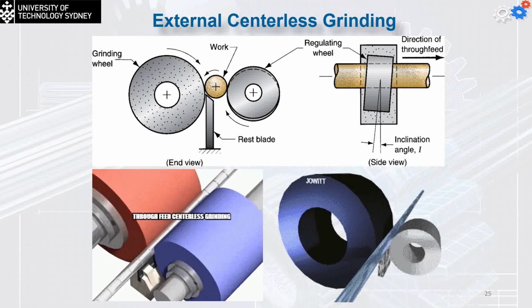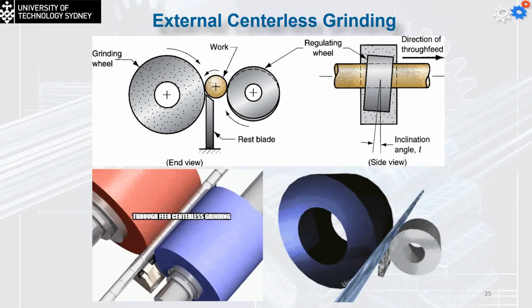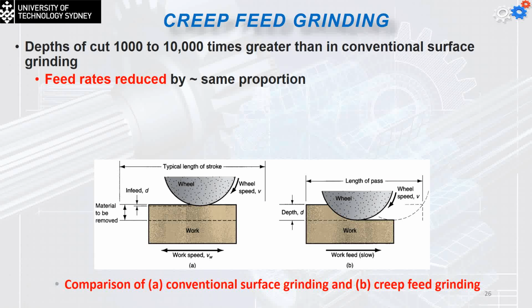We have two different types of grinding, one of which is the creep feed grinding process. Now, that's the normal case, the conventional surface grinding. We just remove the material in a very thin layer to expose a new good surface finish. But sometimes we can use the same process to remove the material at a higher rate to even do the shaping. And that's what we know as creep feed grinding, where the depth is going to be 1,000 to 10,000 times greater than the conventional surface grinding process.